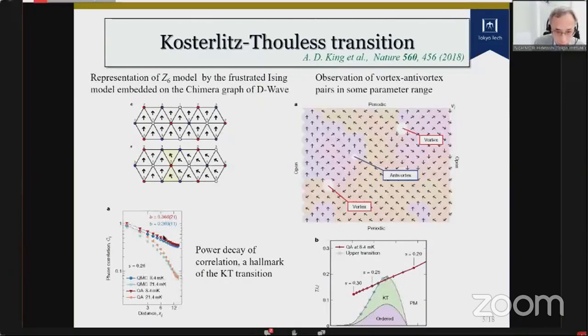And this line represents the power decay of the correlation function within this region, which is a hallmark of the Kosterlitz-Thouless phase. And away from this region, for instance here, the correlation function decays exponentially. So in this sense, they successfully reproduced the Kosterlitz-Thouless phase transition by quantum simulation. This is a very remarkable and interesting example of quantum simulation by quantum annealing.